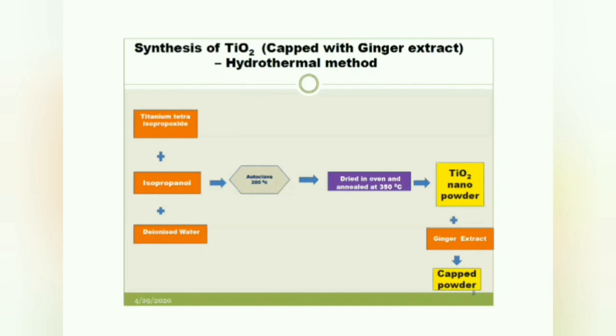You take 10 grams of fresh ginger and boil it in 100 ml deionized water at 60 degrees centigrade, and then filter this with Whatman filter paper. Store this at 4 degrees centigrade. So here I have taken nearly about 4 ml of ginger extract.